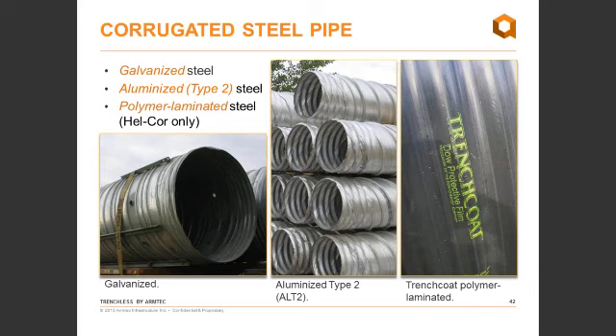So there is the option to supply an aluminized type 2 steel pipe. And what that is essentially, it's a steel pipe with a pure aluminum coating. And the coating actually holds up very well because aluminum works a little bit more as a self-healing barrier coating as opposed to a galvanized zinc coating, which is more of a sacrificial coating.